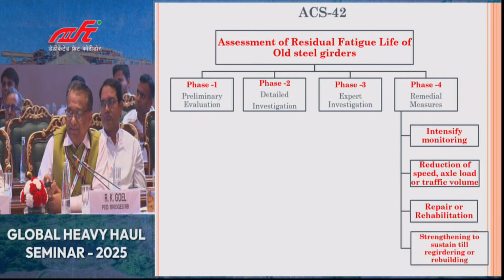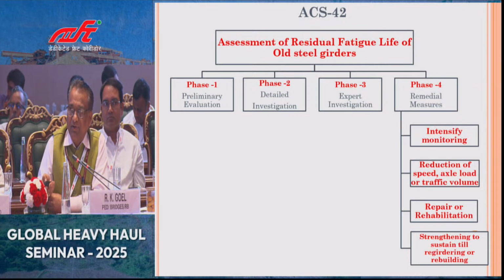So a phase-wise assessment program has been suggested again in the Indian Railway Bridge Manual. In phase 1, preliminary evaluation based on the documents only, and detailed investigations by refining the parameters like GMT, actual GMT, what is there, what is the actual speed. All those parameters are to be assessed more realistically, and then again analysis, and if the structure is still found to have less fatigue life, residual fatigue life, then we have to go for expert investigation who will do the instrumentation for a period of say 15 days or 1 month, the representative period of the year, and then make the actual time histories and histogram, stress range histograms to work out the detailed fatigue assessment of different members and work out the residual fatigue life.